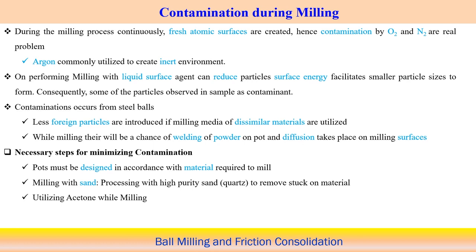So another point is that while milling there will be a chance for the welding of the powders on the pot, and diffusion might take place also on the milling surfaces. So that is always there. There is a chance that the grinding media can diffuse with the particles, and they can create some kind of contamination of the particles generated. So that can be another issue or problem associated with this.